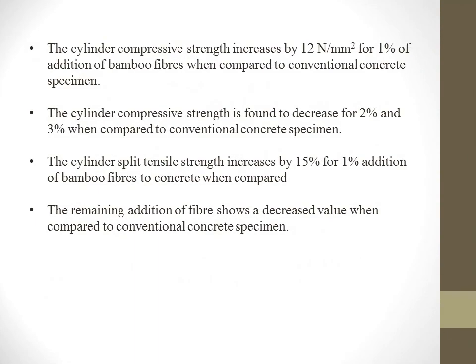The cylinder compressive strength had increased by 12 Newton per mm square with 1% addition of bamboo fibers, and the cylinder compressive strength is found to decrease for 2% and 3% respectively. The cylinder split tensile strength increases by 15% for 1% addition of bamboo fibers, and as usual with the remaining addition of fiber, there is a decreased value of split tensile strength.